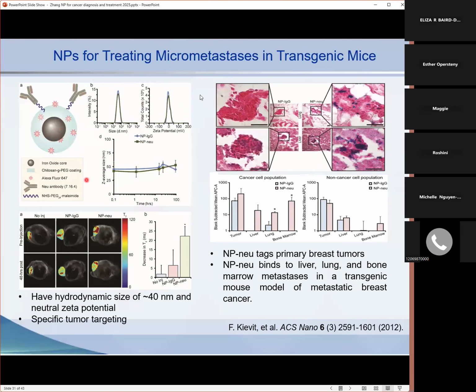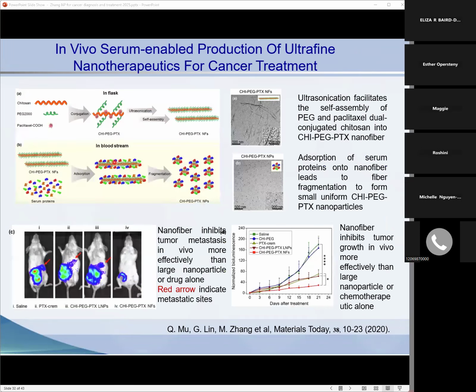So the first example is that we use a nanoparticle treating micrometastasis. Again, we use a nanoparticle with an antibody. We are not talking about chlorotoxin anymore. We found the nanoparticles are small size, stable, and can specifically target the tumor region. After injection of nanoparticle, we really demonstrated that these nanoparticles can target the metastasis. This is a very early work, and I'm going to show you some of the recent work.